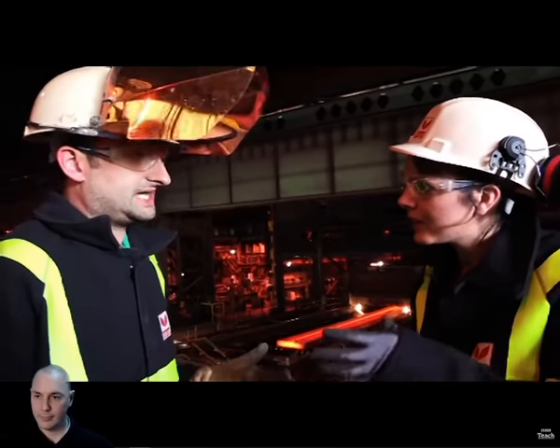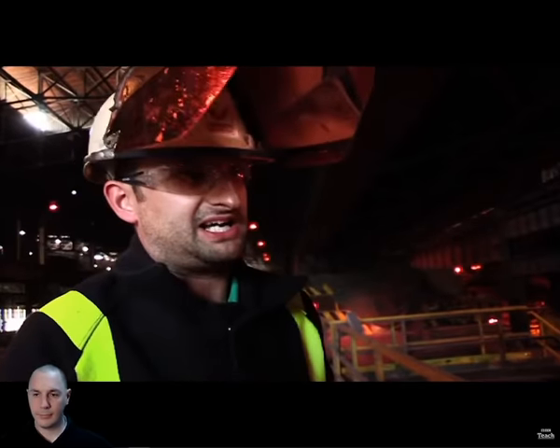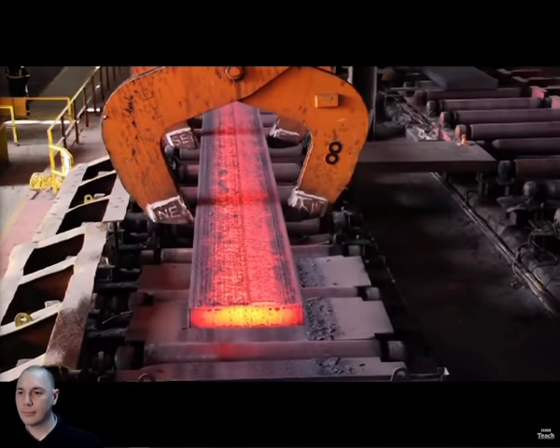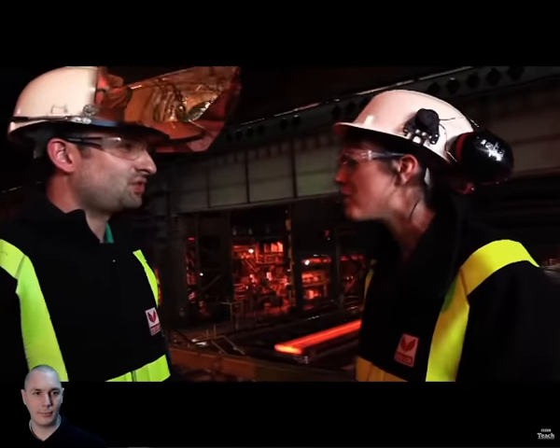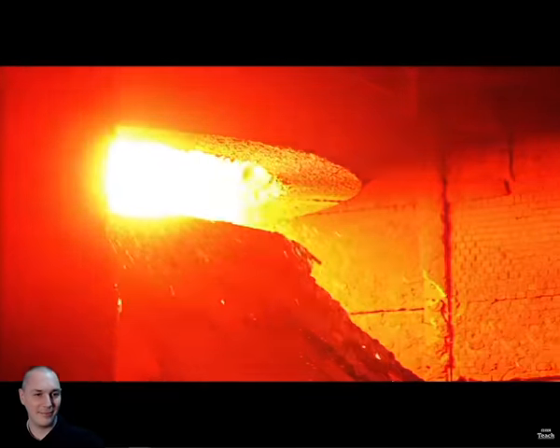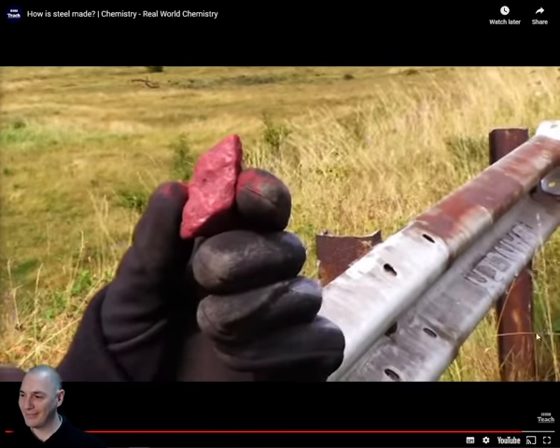The scrap metal and liquid iron go into a converter — a vessel that holds all materials ready to be turned into steel. In the basic oxygen steelmaking process, an oxygen lance is sent into the vessel, hovering about four metres above the steel bath, blowing oxygen at 750 cubic metres per minute. The oxygen hits the carbon in the steel, producing CO and CO2, removing the carbon. Customers require steel with different carbon levels for strength and flexibility. The finished liquid steel is poured into a copper mould shaped like a slab — still about 1,400 degrees — and each slab is about 15 to 20 tonnes.